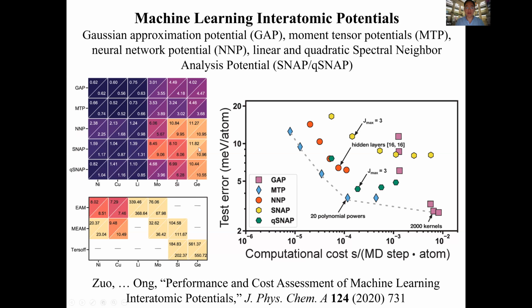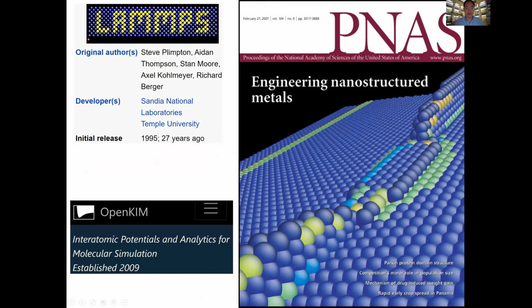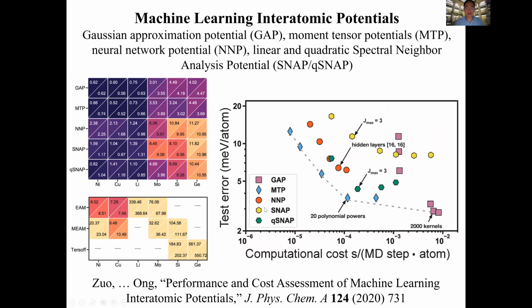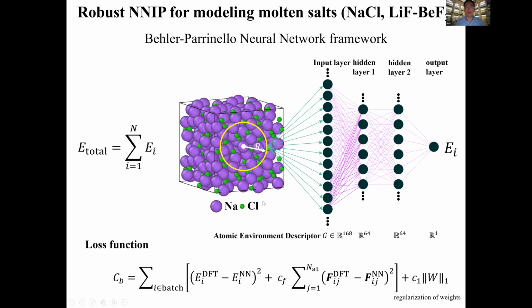However, I just want to say that most of the machine learning potentials today are for unary, binary, or up to maybe 4 or 5 elements. We did a survey of how many potentials are in the OpenKIM database for, let's say, more than 3 atoms, and it's less than 1% of the potentials.